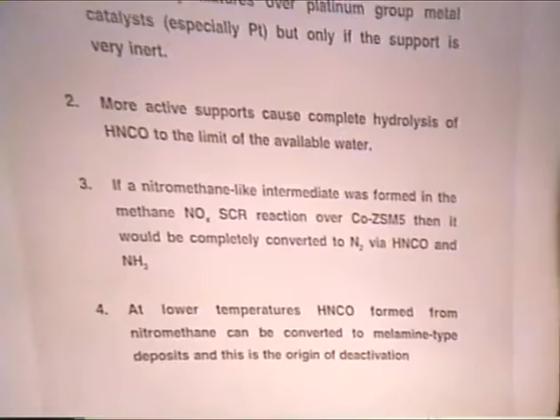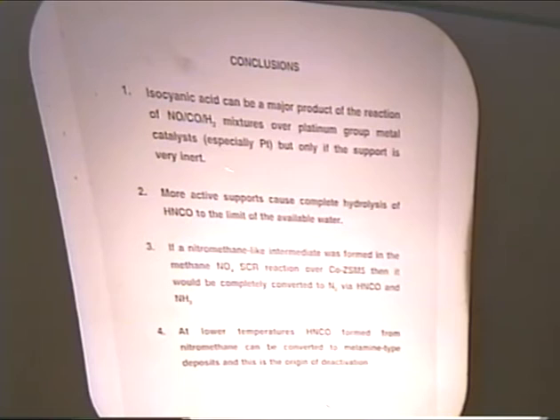Conclusions from that work that we presented. Firstly, that isocyanic acid can be a major product of the reaction of NO, CO, hydrogen mixtures over all the platinum group metals that we've looked at, especially platinum, but only if the support is very inert, and more active supports give complete hydrolysis of the isocyanic acid. The second conclusion is that if a nitromethane-like intermediate was formed in the methane NOx SCR reaction over cobalt ZSM5, then it would be completely converted to nitrogen via HNCO and ammonia. But at lower temperatures, isocyanic acid formed from nitromethane can be converted to melamine-type deposits, and that causes the deactivation of the catalyst, which is so prominent in these systems. Thank you for your attention.